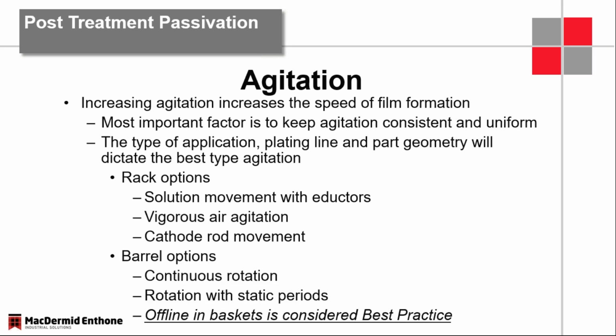Barrel, not so much. You could have continuous rotation. You could have rotation that just turns maybe a quarter turn every 15 seconds. But because it's the gelatinous water-based film, you're going to get some scratching, especially on black Passivates because they're thicker. The Passivate film is going to scratch. So best practice is to do offline basket passivation from barrel plating operations. That will produce the best color and the best corrosion resistance. Can't stress that enough. Extremely important. Why go through all these efforts to produce a substandard part that looks bad and doesn't perform the way you think it would? Do it offline. That's the way to do it.